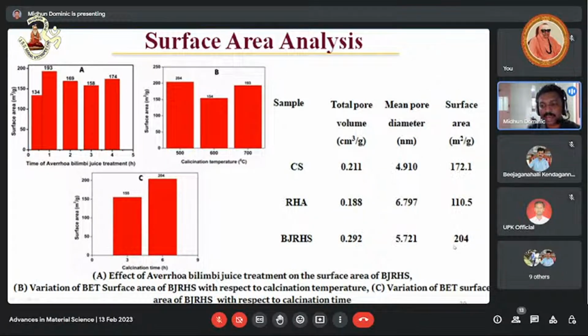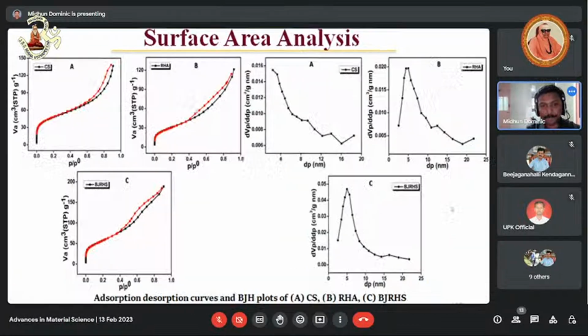But for BJRHS, the surface area is drastically improved. Rice husk ash has a lower surface area, and BJRHS is around 204. So we could prepare a nanosilica with excellent surface area, greater than that of commercial silica and rice husk ash. And these are all the BET adsorption, BJH plots and pore size distribution.